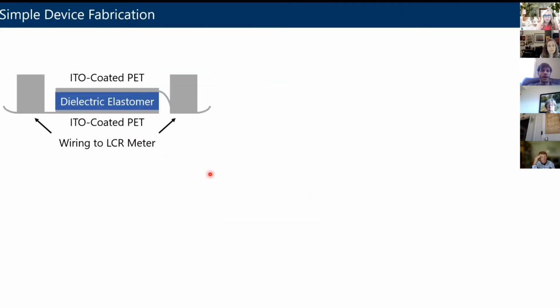Now, making these devices, again, is really simple, very straightforward. Parallel electrodes. In this case, we're using indium tin oxide coated polyethylene terephthalate. So they're a little bit flexible because it's a conductor on a polymer. And it's transparent because indium tin oxide is transparent, and so is polyethylene terephthalate. We wire it up to an LCR meter.